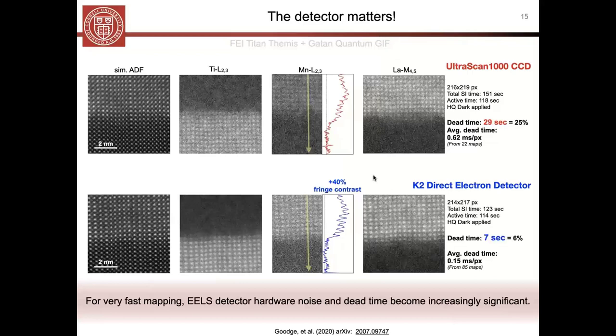Again, if we compare those same statistics for the direct electron detector, what you can see is that the dead time has reduced actually by a very significant factor, from almost 30 seconds down to 7 seconds. And as a total percentage of the map time, we've reduced it by about a factor of 4. And so the average dead time per pixel, again, is greatly reduced in the direct detector. And so this fast readout allows us to take actually better data in less time. And so that's really very critical for trying to do this atomic resolution EELS mapping.